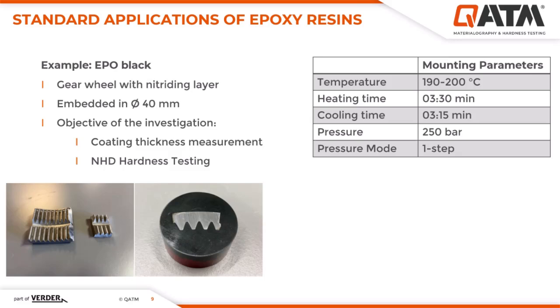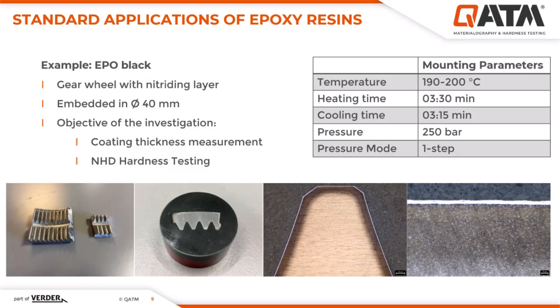So the mounted sample was ready. After 3 grinding steps and 1 3-micron polishing step, the sample was fully polished. It can be seen that the layer was well protected during the mounting and a sharp-edged preparation was possible because the epoxy resin is very hard. This allowed the measurement of the nitrided layer.